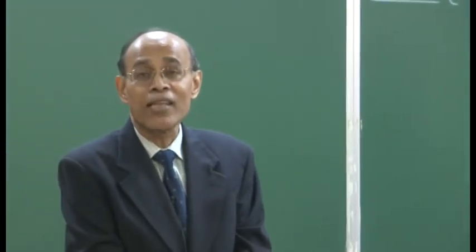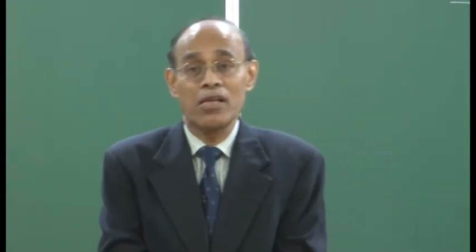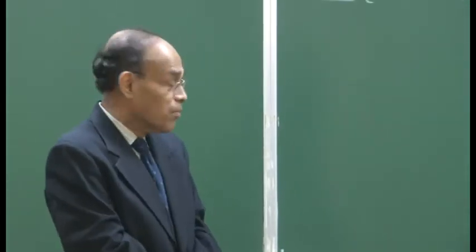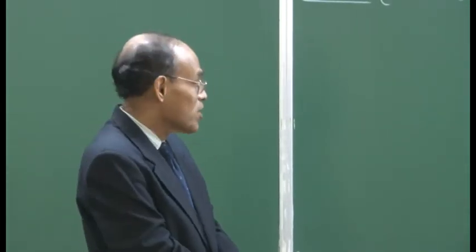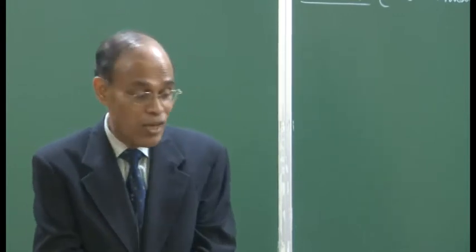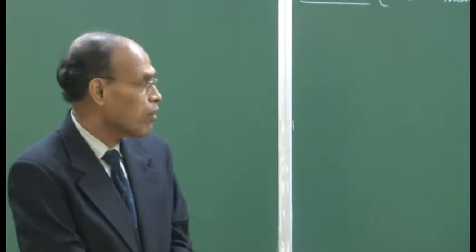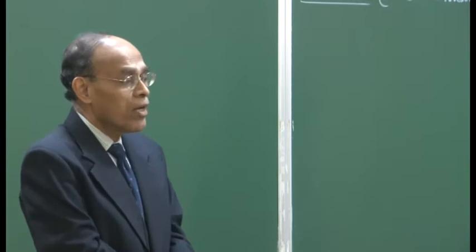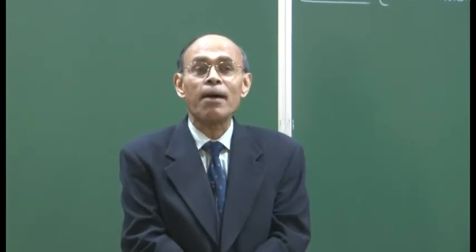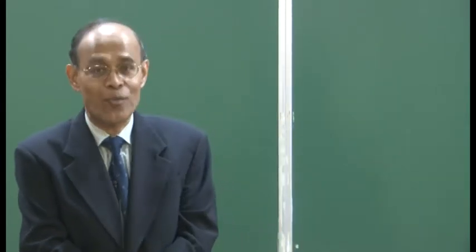We have seen in the context of enthalpy balance that if carbon oxidizes to carbon dioxide, in that case 395,000 kilojoules per mole of carbon, that much of heat energy is released, and the order of magnitude is similar for silicon dioxide also. The silicon oxygen bond is very, very strong. So, if you have too much silicon, for example, in that case what happens? The steel making is not going to be economic.